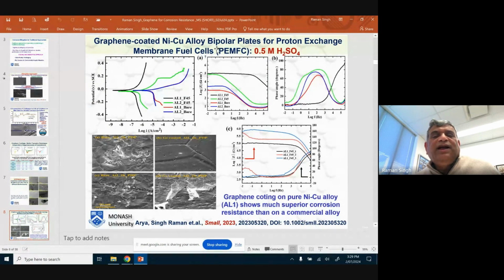And when I have a suitable alloy, like an alloy of nickel copper with a particular composition, it gives me very good corrosion resistance. Once again, this intercept gives me corrosion resistance, and you can see even if I'm trying to force it to corrode by imposing anodic potential, it is not corroding much, whereas the pure nickel would have corroded at a very rapid rate. And then even another technique, electrochemical impedance spectroscopy, gives very reproducible results showing that it is very resistant to corrosion in this aggressive environment. Seeing is believing once again: the bare nickel copper alloy would have been attacked very easily, whereas the graphene coated one does not corrode much at all.